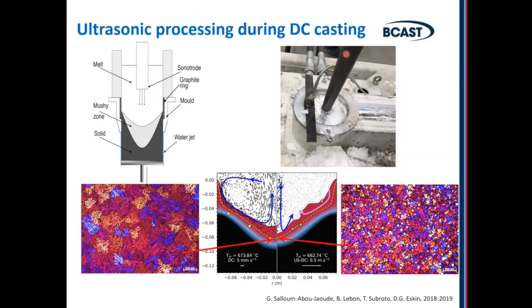And also, as you saw in previous slides, here we use mostly, and most of the people when they study this or try to use it, they use treatment in the mold. This is a DC casting mold. So your source of ultrasound is embedded into the mold, which means that if you have numerous molds, which is currently the practice when you cast extrusion billets, you can have 28, 64 molds on one table, you need to put an ultrasonic source in each of them, which of course is practically not viable. So if we can move the treatment to the flow, to the trough from which melt comes into the molds, we can scale up the process.